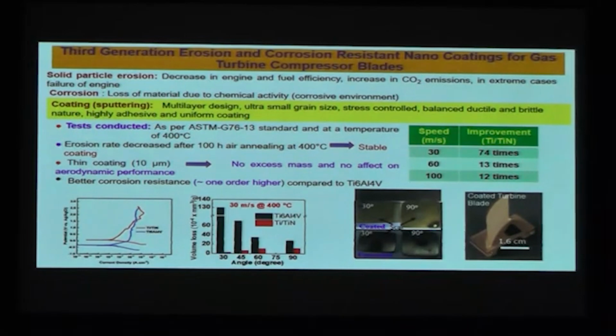So here we have developed this titanium nitride-based coating, that is TiN, and this is once again a multi-layer coating by the sputter coating process. It has very good erosion resistance, about 74 times higher than that of the bare substrate, even at a speed of 30 meters per second. At higher erodent speed also, the erosion resistance is reasonably good. We achieved up to 12 times higher than the bare substrates. And it also has very good corrosion protection.